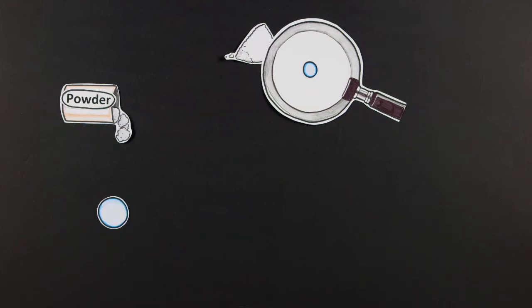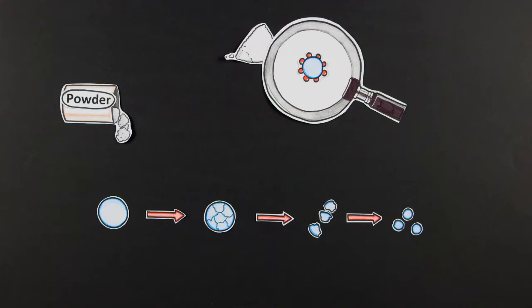The source material is crushed by cold, wet grinding. This process results in irregularly shaped segments which are smoothed into round spheres in the next step. Applying a final nanoscale surface coating ensures that the required flowability and optimized bulk density of the powder are achieved.